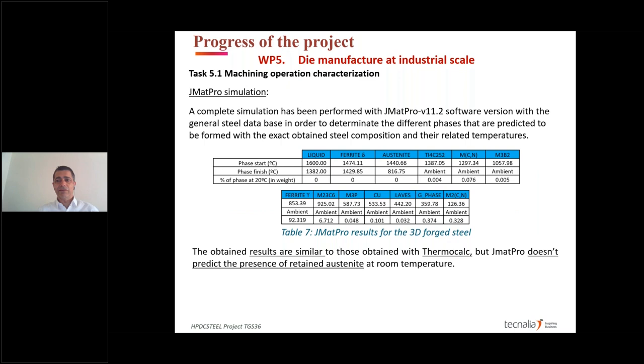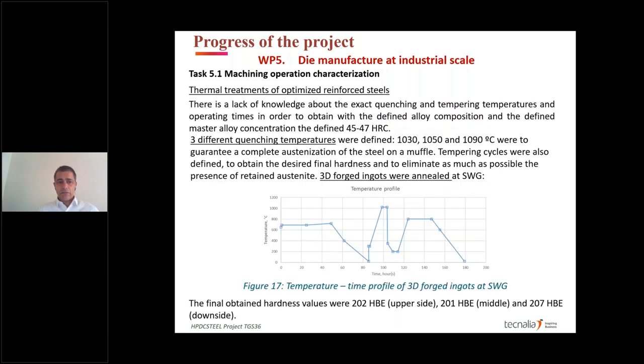The only difference that we saw is that JMatPro was not capable of predicting the presence of retained austenite at room temperature, so we had to define the thermal treatment. This was a key point because we knew nothing about that. We knew it was very important to define the temperatures and times and so on, but we must submit data. So we put three different quenching temperatures: 1030 degrees, 1050 and 1090.